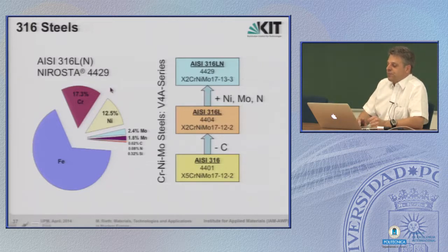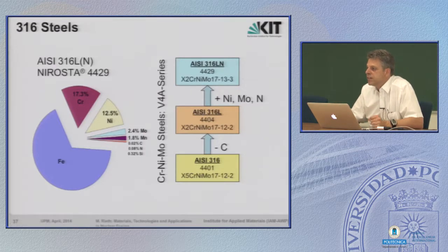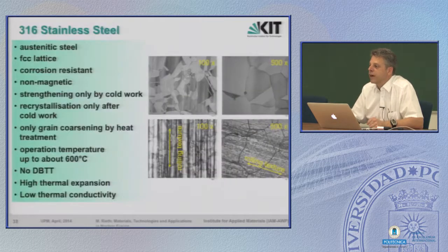That's a very broad application for these steels. The usual 316 without any addition has this composition. Then there are some subversions of these steels with a lower carbon content, called 316L. And with a higher nickel, molybdenum, and nitrogen content, it's called 316LN. And with an even more precise specification, it's called 316LN ITER grade.